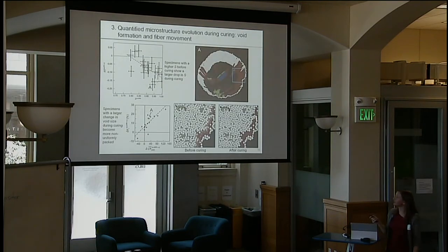The third thing that we've looked at is quantifying the microstructure evolution during the cure process. So during curing, the polymer releases a bunch of gas, and this gas needs to escape. So often what we actually find is that the specimens that performed really well in the last step and had a really high saturation have the largest drop in saturation during curing because they need to form bubbles for the gas to escape. And this is a problem because when these really big bubbles form, they actually cause a significant amount of fiber movement, which is shown here with this red void, pushes a bunch of fibers out of the way. And the bigger the bubbles that form, the more non-uniformity we find in the fiber bed later, which is a problem in later steps in this process.